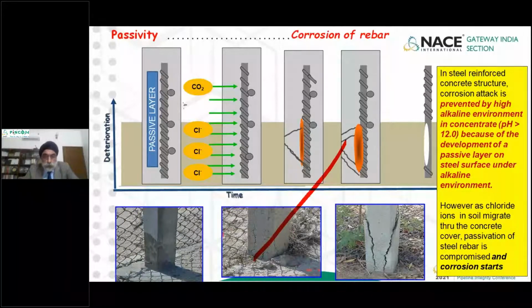This is being shown in the 3 photographs on the bottom side. If you see the first photograph, the concrete of a foundation post is completely okay. Over a period of time, you can see small crack formation. And then finally, the entire cover of the concrete has fallen down, exposing the steel to the environment. Once the steel gets exposed to the environment, this is what is going to happen. The diameter of the rebar starts to reduce, and then eventually the reinforcement steel will collapse, causing the collapse of